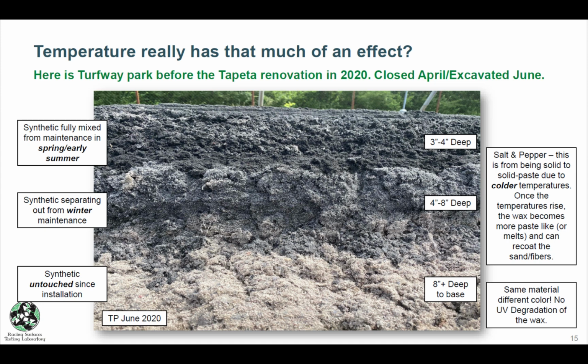And so the track wasn't actually truly fully worked in the hotter, warmer conditions. And what ended up happening is that on the top layers of the track, you can see that the wax is very black. The track is very black. We have very good coating of the material. But if you go down 3 to 4 inches, we actually can see the effects of the wax separating out just from the winter maintenance. It has this salt and pepper look to it.